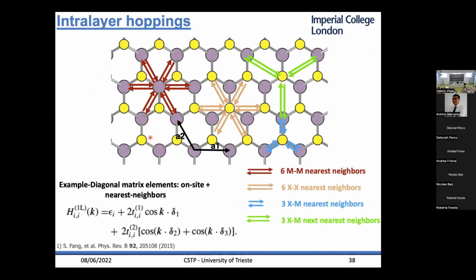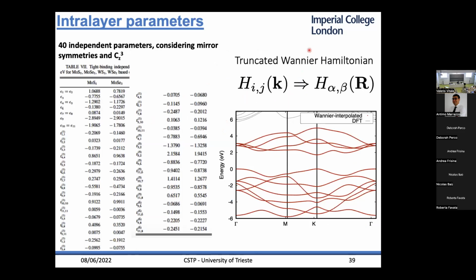And then we basically adopted a tight binding that goes up to third nearest neighbors. So basically, we consider the first nearest neighbors of chalcogens with metal, and then second nearest neighbors with chalcogens and metals with metals, and then third nearest neighbors again with chalcogens with metals farther away. Right? And if you do all of that and you consider symmetries, you get 40 independent parameters for the monolayer.